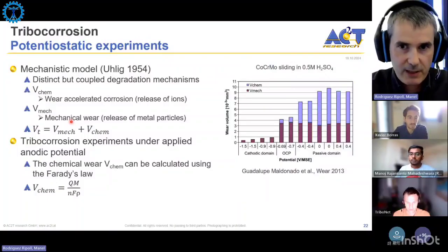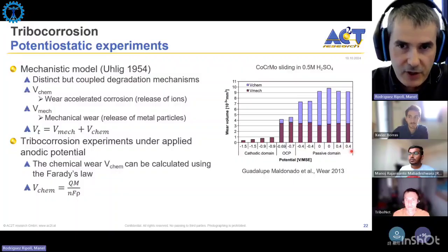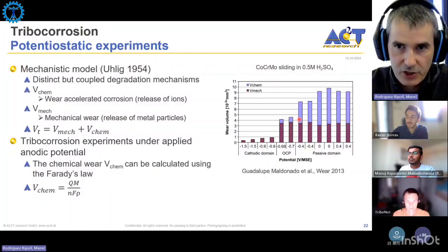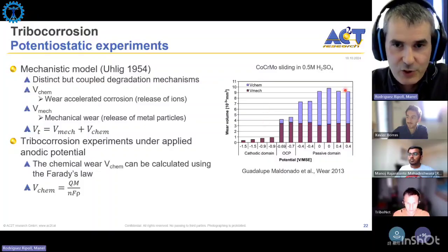And then you can make, for example, this kind of graph where you plot the total wear volume as a function of the potential, and then you can see, for example, that with increasing potential, the total wear increases because we increase the thickness of the passive layer and we destroy this passive layer.